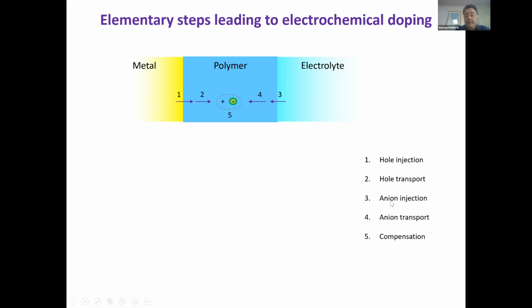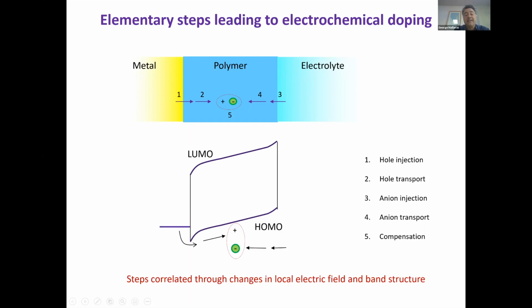They don't happen necessarily in this order. The order in which they happen is determined through local electric fields and band structure of the material. You can even start putting an energy level diagram for these processes together, same as a light emitting diode, and start describing the process. However, so far, what I have described is a purely capacitive process. What I'm telling you is that the electrochemical doping of a polymer is a purely capacitive process. There is no exchange of electronic charge between the polymer and the electrolyte. It's just a compensation effect that forms little capacitors somewhere in this structure.